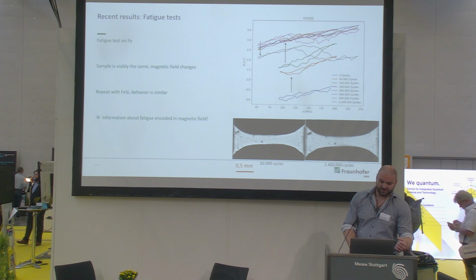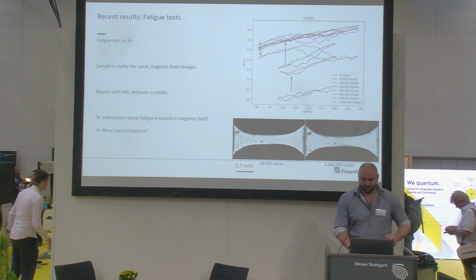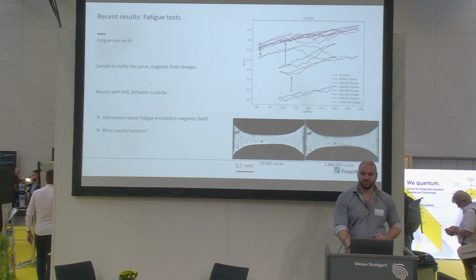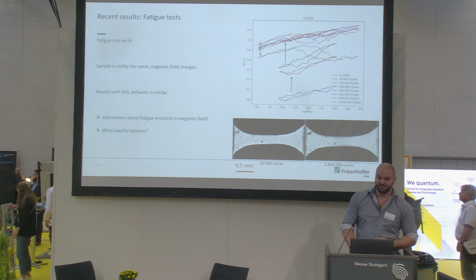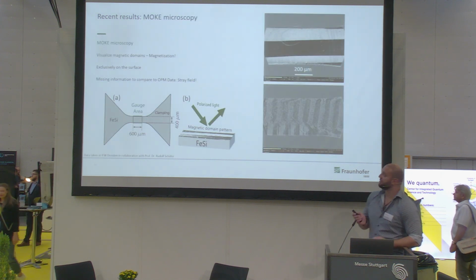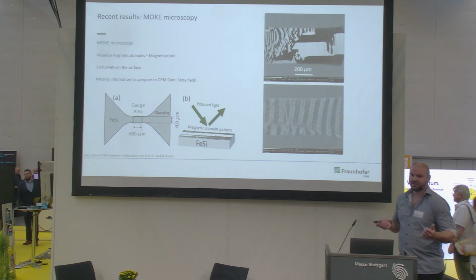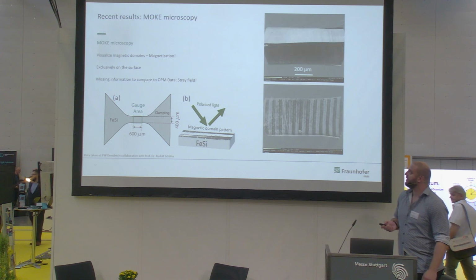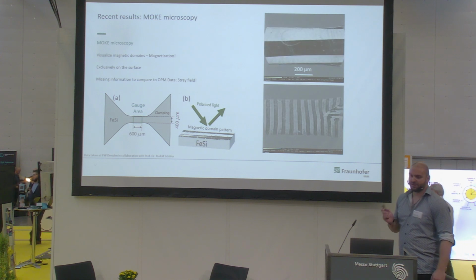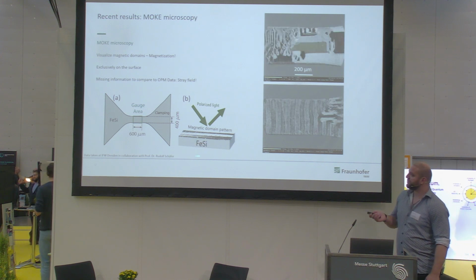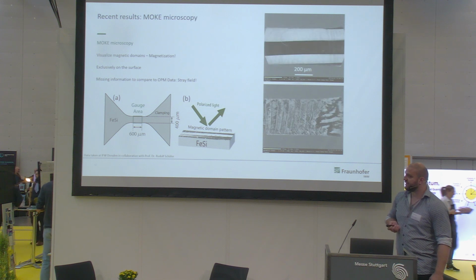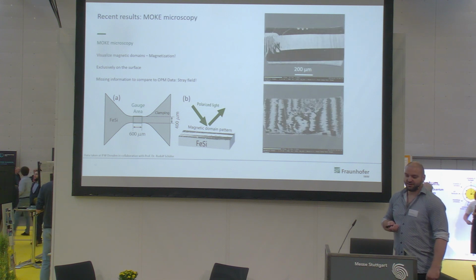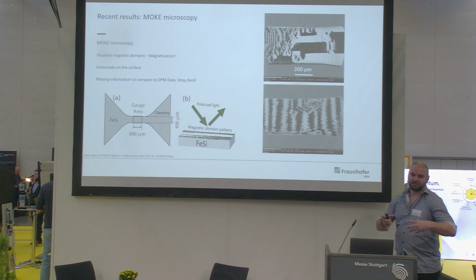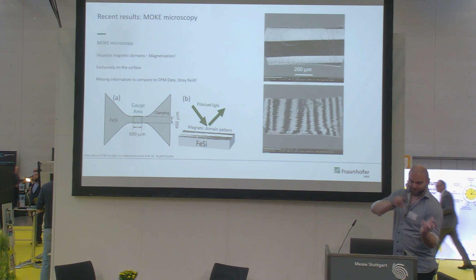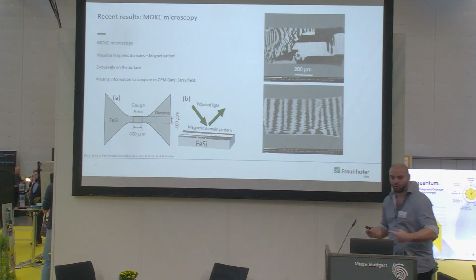And the question is now, okay, what exactly is happening here? So what people usually do to investigate magnetic states in these samples is magneto-optic Kerr microscopy. It's a standard technique, very well known, and especially on iron silicon, this is very well known. We did this measurement together with Professor Rudolf Schäfer at IFW Dresden. And basically, we just took our whole tensile test apparatus, put it in a car, and drove it to Dresden, and we built it there under their Kerr microscope.